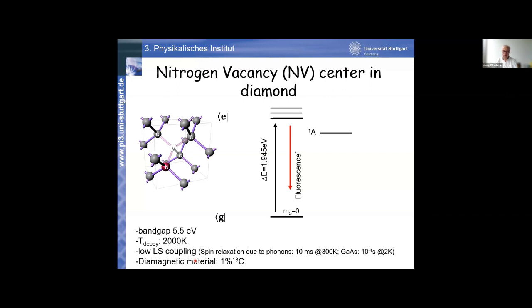All right, so now how does a typical experiment look like? The electronic ground and optically excitable first electronic state have a delta E of around 2 electron volts. This is 640 nanometer or so of a transition wavelength. And in most cases, if you excite the system here, it returns straightforwardly by emitting fluorescence, or in solids people typically call this photoluminescence, to the ground state.